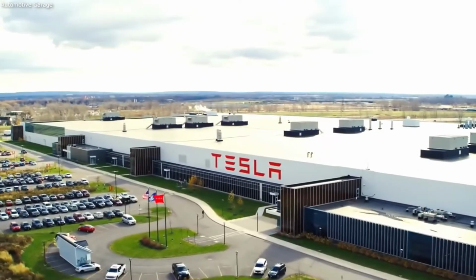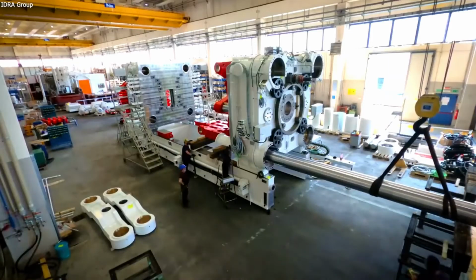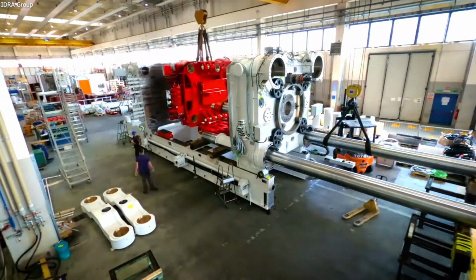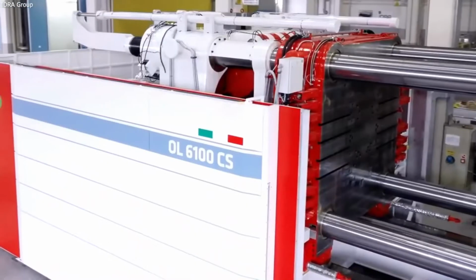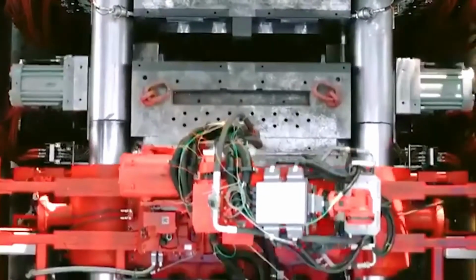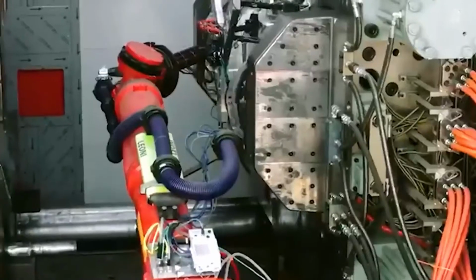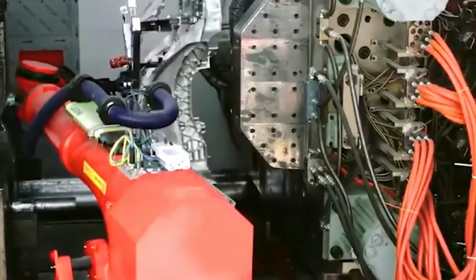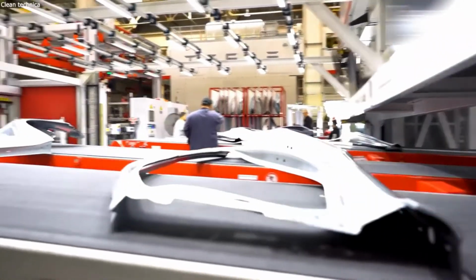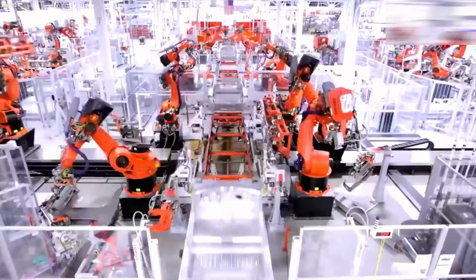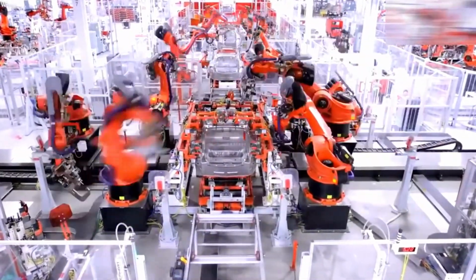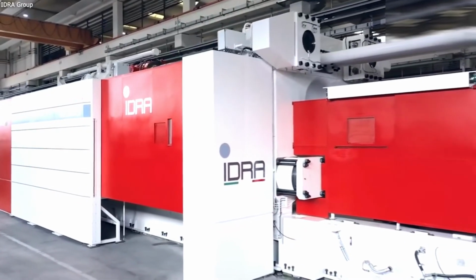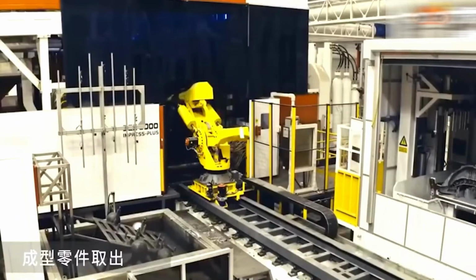For the Tesla's GigaPress-based casting operation, ingots and offcuts of aluminum are melted in a natural gas-powered melting oven operating at 850 degrees Celsius. Slag in the form of aluminum oxide is mechanically removed from the surface, and the rest of the liquid metal is pumped through the heated pipes to an enclosed warming oven operating at 750 to 850 degrees Celsius, heated using 400 kilowatts of electrical power. To prevent the formation of oxides, a tank blanket of nitrogen gas covers the molten aluminum, which is circulated to maintain an even temperature. Argon gas and a rotary degasser are used to remove impurities, with a silicon carbide filter removing most other particles larger than 25 micrometers.